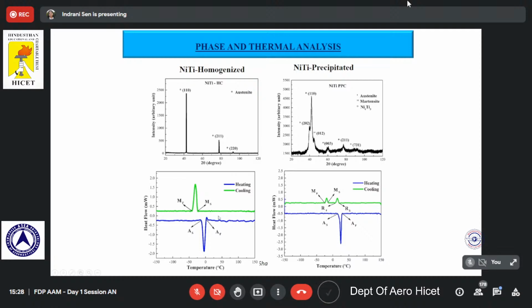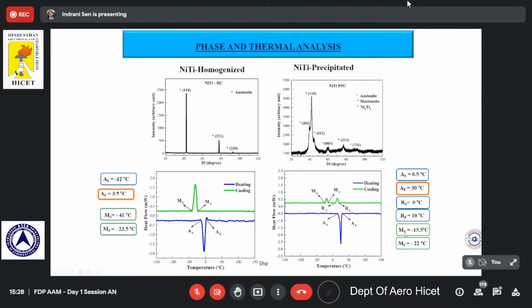In this case, on the other hand, we can see that the temperatures have been changed and there are double peaks in case of the cooling cycle. So there is the R phase conversion first, which then converts to martensite. And finally, this R phase conversion starts at 0 degree, and the austenite finish temperature is something like 30 degrees. So it's very close to the room temperature, or if we are considering room temperature as 300 K, actually it is exceeding the room temperature to a certain extent. So that also indicates the possibilities of presence of a little bit of martensite at room temperature. Okay, also these double peaks do signify that there are precipitates present in the structure.